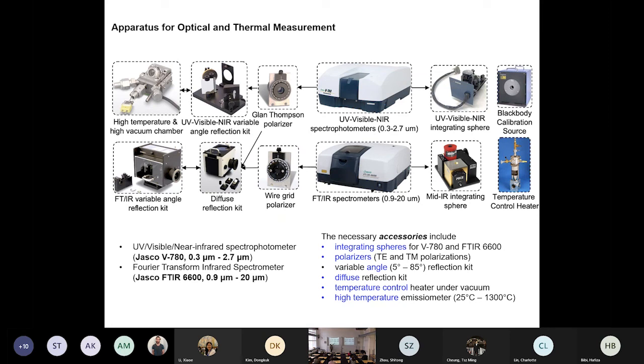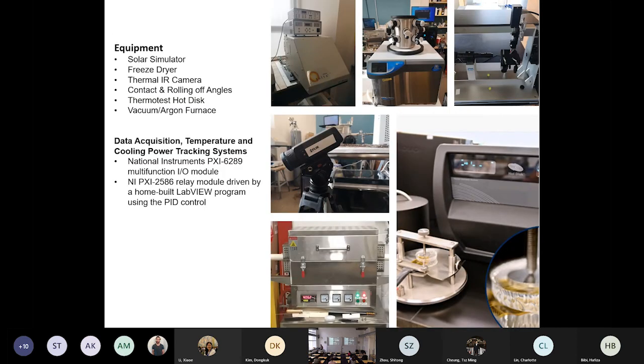We have 2 integrating spheres, polarizer and different kits for the different measurements, for different temperature, for vacuum, and also for diffuse reflection measurement. And also everything we have in my lab. So we have a vacuum furnace, up to 1300 degrees Celsius. We also have another furnace, the muffle furnace, that could heat up the sample up to 1700 degrees Celsius in my lab. And thermal camera, solar simulator, freeze dryer used to fabricate hydrogel material. That one is used to measure the contact angle. Oh, I forgot to mention that.